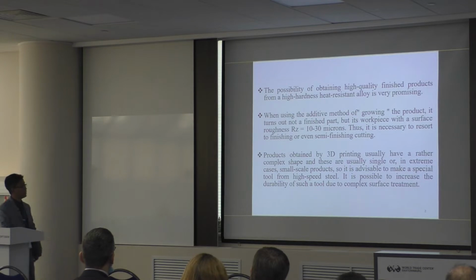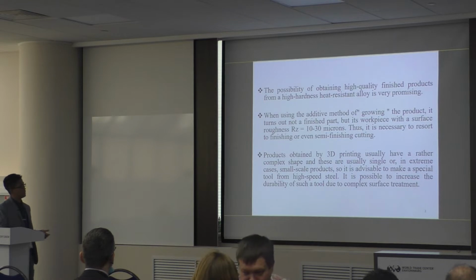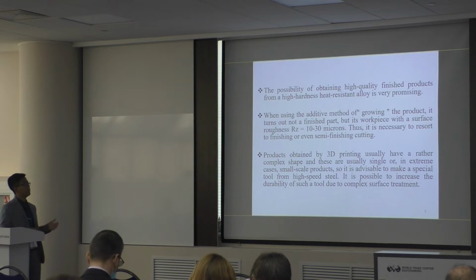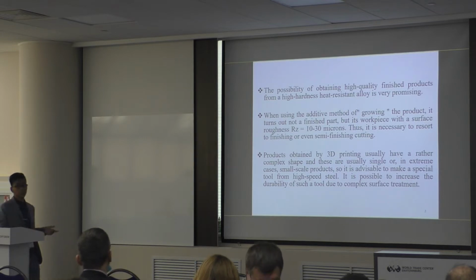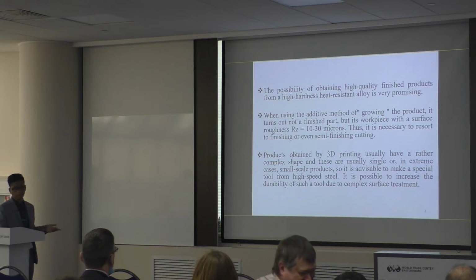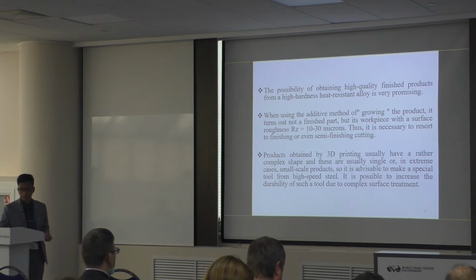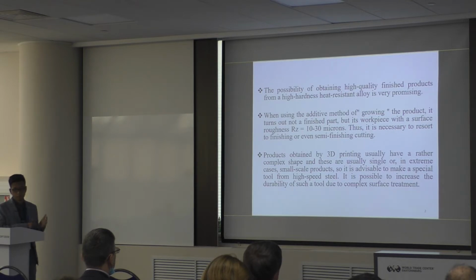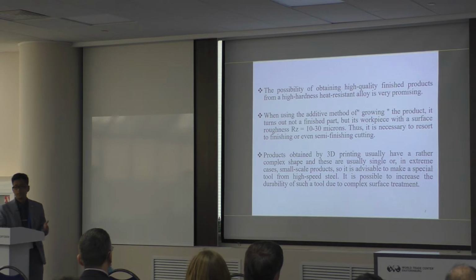Products obtained by 3D printing usually have a rather complex shape. These are usually single or, in extreme cases, small-scale products, so it is advisable to make a special tool from high-speed steel. It is possible to increase the durability of such a tool due to complex surface treatment. The paper compares the durability of a tool made of high-speed steel with complex surface treatment with a milling blade made of titanium alloy obtained by selective electron beam method and using traditional technology.